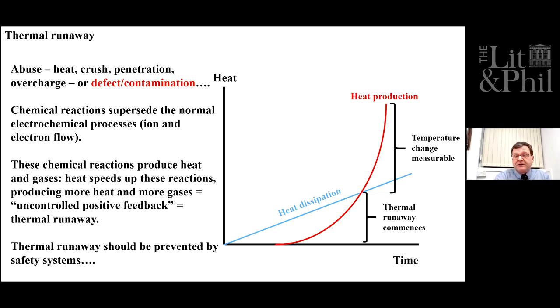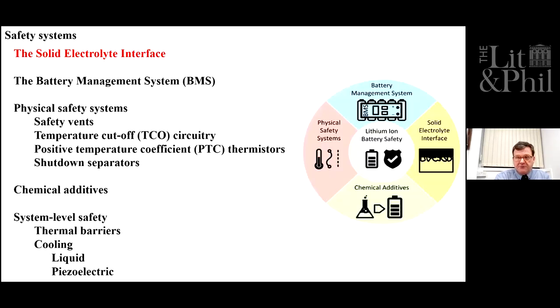Now, thermal runaway should be prevented by all the safety systems that are present in lithium-ion batteries. The first safety system is a serendipitous one. It's the solid electrolyte interface. Lithium-ion batteries are thermodynamically unstable. In other words, they should not exist. As soon as the solvent hits the fully charged graphite electrode, in other words, the lithiated graphite, it generates hydrogen and other gases and heat. And it should just go into continued thermal runaway, but a protective layer forms on the graphite during that first charge that stops the solvent touching the lithiated graphite, but still allows lithium ions through.